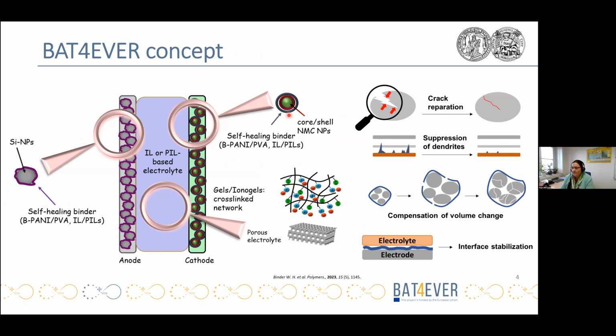In the scope of the BAT4EVER project, we are trying to introduce self-healing polymeric materials in different parts of the lithium-ion batteries. Self-healing polymers in general are polymers which are able to spontaneously repair themselves after damage. And we are working on one side on the self-healing polymers which can be used as the binders for electrodes, which are able to compensate the volume changes of the electrode during charging and discharging, and thus preventing the cracking and pulverization of the electrode with time.